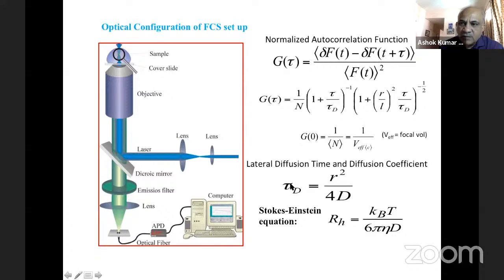And then you study the diffusion of that, and through this mathematical structure which is taught in statistical physics and statistical chemistry, where you look at the motion of a particle through either fluorescence or through light scattering, through diffusion. So here we use fluorescence, and this is what is called the autocorrelation function. From that you can generate the tau, the relaxation time, the diffusion coefficient, and the size of the particle. R is called the hydrodynamic radius, and this is the famous Stokes-Einstein equation, which you can also use using light scattering. But in confocal fluorescence correlation spectroscopy, what is important, you are looking at one particle at a time.